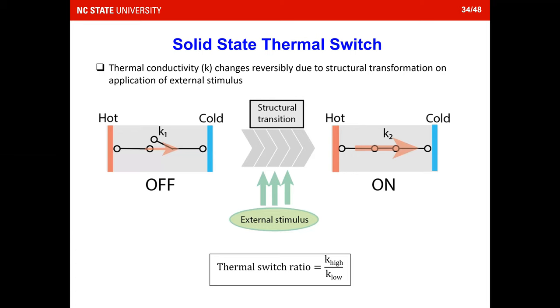So thermal conductivity actually can be changed reversibly if you have structural transformation, right? Based on the understanding of a solid, we know that it really depends on the structure you have. So if you can have reversible structure transformations, probably you can switch your thermal conductivity. And by applying those external stimuli, if you can switch the thermal conductivity, then you definitely can control the temperatures locally or on demand, right?